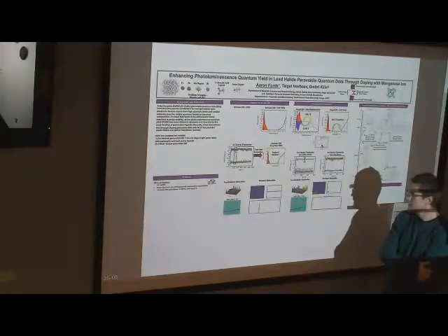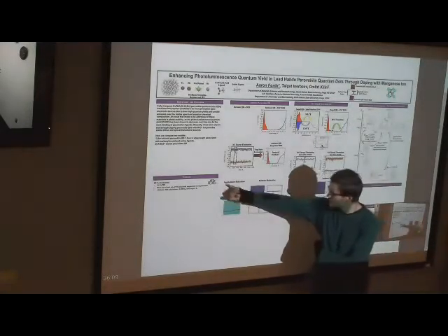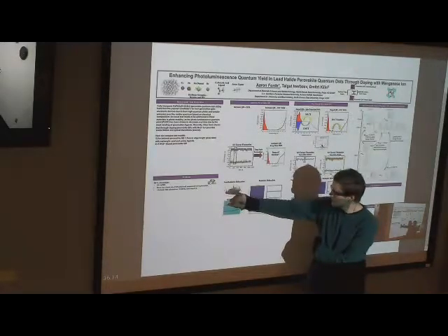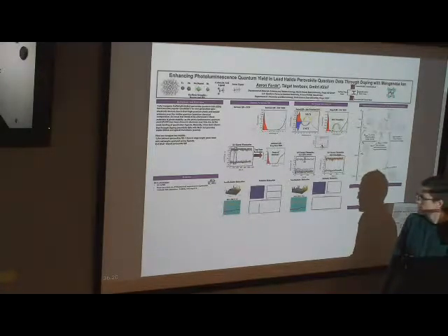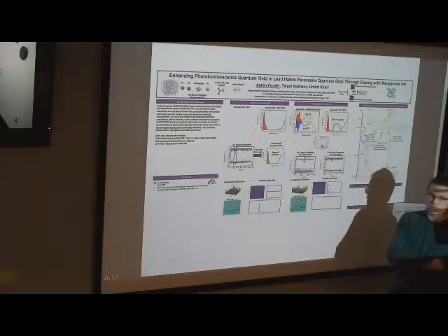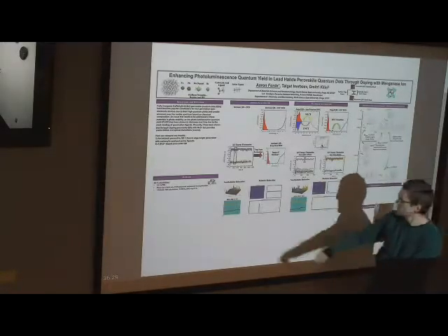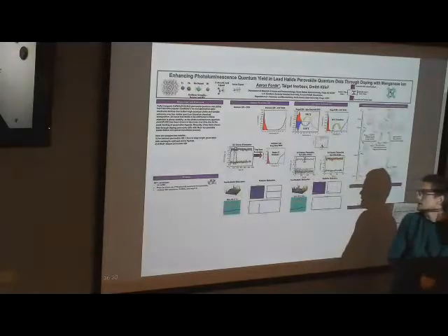From molecular dynamics, we could go on to our excited state dynamics. For non-radiative relaxation, we use Redfield theory, and these are our Redfield tensors, which basically describe coupling between orbitals, between states, and the off diagonal. If you zoomed in on the image, all the diagonals would be 0, and states close to each other are going to have high bars, and then further away you get these decaying here. The very high peaks indicate a very high rate of non-radiative transition between orbitals.